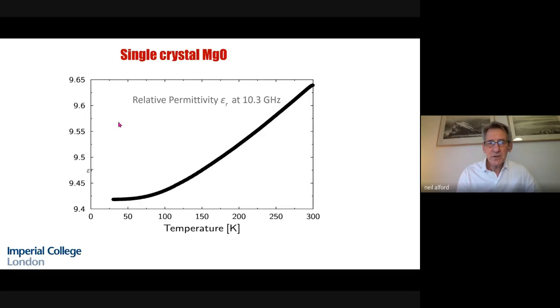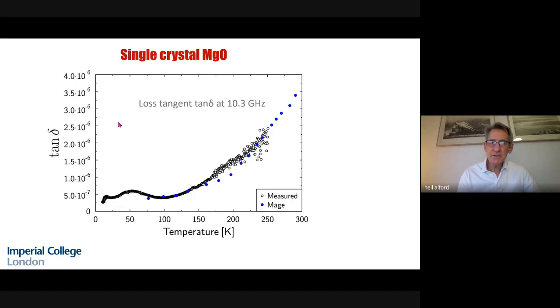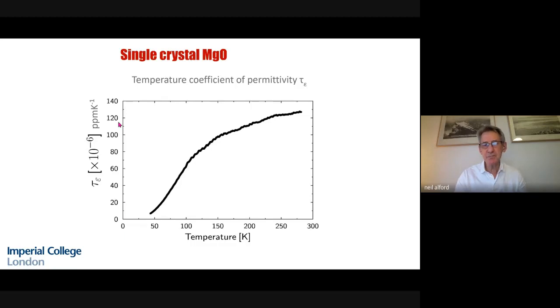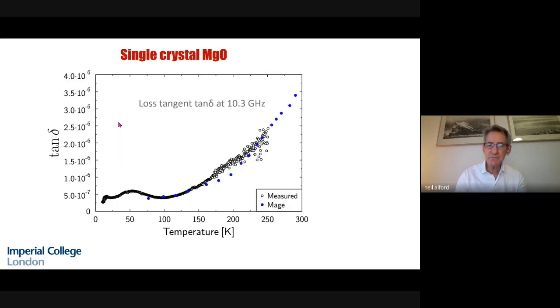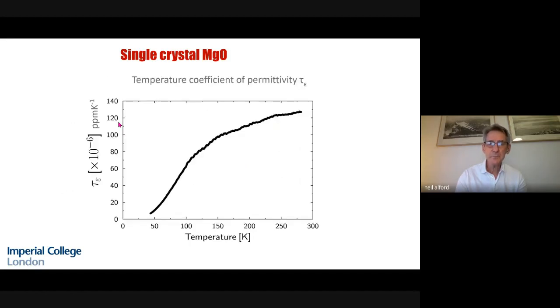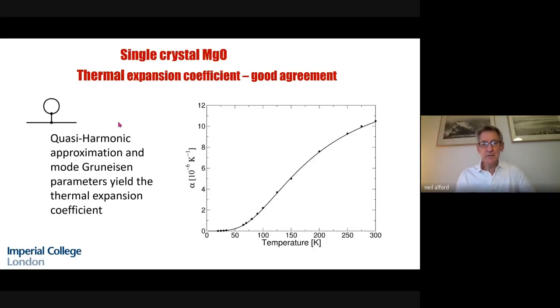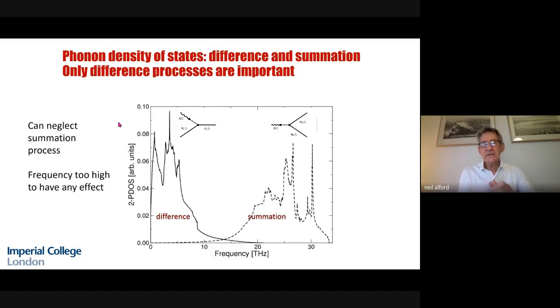So here is the single crystal of magnesium oxide, and here is the relative permittivity. And there's a nice smooth curve, the relative permittivity. And here is the loss tangent for the same single crystal at around 10 gigahertz. And we see that it's not as smooth as the one that we had before. And this is due to defects and impurities in the single crystal itself. And then we can also look at the temperature coefficient of permittivity. So these properties are fairly straightforward, but this property is not so easy to predict. So thermal expansion, pretty good agreement. That's not a problem. And then we need to look at the phonon density of states, the difference and summation processes. And for the loss, only the difference processes are important here.